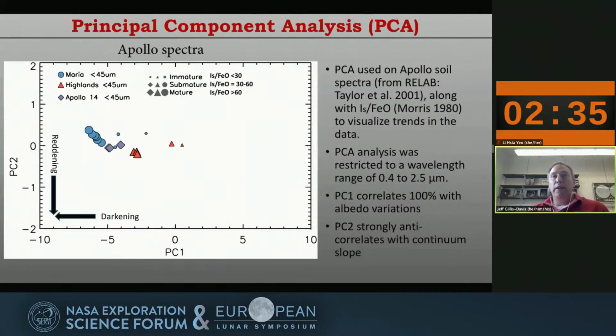We can take these spectra, and this is work that Heather Kaluna has done for this project, where we do principal component analysis. We wanted to compare this to real Apollo samples to see how faithfully we're reproducing our weathering. On the bottom we have PC1, which corresponds mostly to albedo, and PC2 on the y-axis, which mostly correlates with the continuum slope. We have Mare, Highlands and Apollo 14 samples with the different color codes. The size of the samples correlates with maturity.